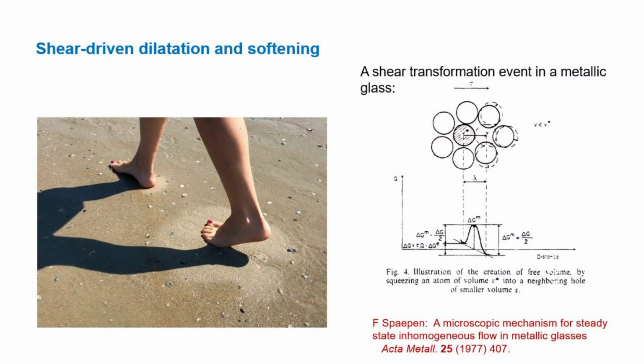So this is somebody walking on a wet beach. You'll detect that the sand goes dry around the footprint. That's because when the sand is deformed, the grains have to move over each other, and the system as a whole has to expand, so that the aggregate of sand grains occupies a larger volume around the deformation, but it still only has the same amount of water in it, so it actually raises the sand proud of the water. There isn't enough water to keep the sand equally wet. And it's an expansion due to some local rearrangement. Well, that could be perhaps what's going on in our metallic glass. It was proposed. Or it could be that this liquid-like layer really does reflect heating.